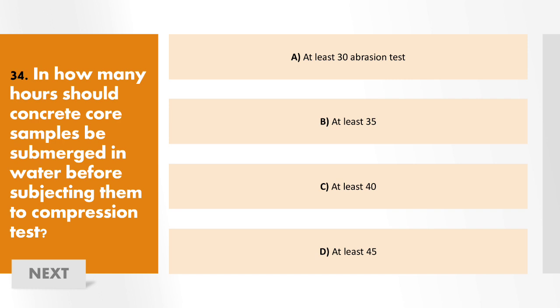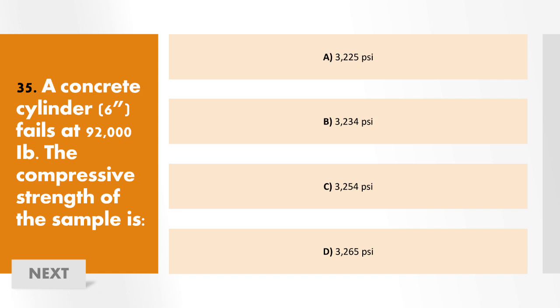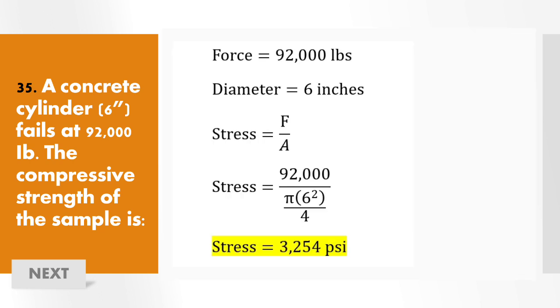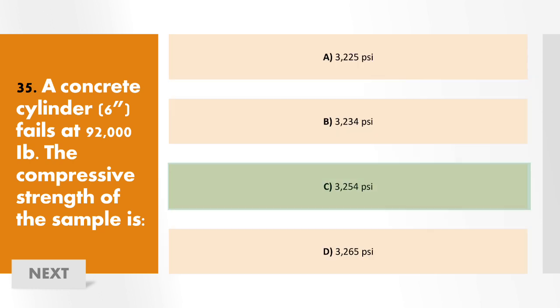For number 34, ASTM C42 states that submerge the test specimens in lime-saturated water for at least 40 hours immediately prior to making the compression test. So the answer is C. For number 35, since we have a force which is 92,000 pounds and a diameter of 6 inches, to find the compressive strength, we can use the formula for normal stress and get the answer 3,254 psi.